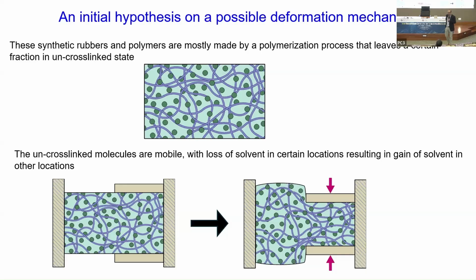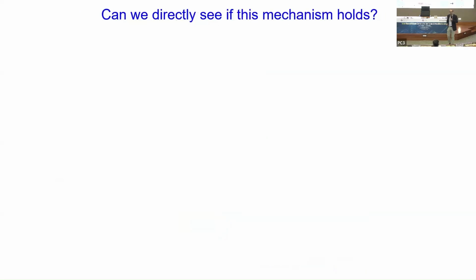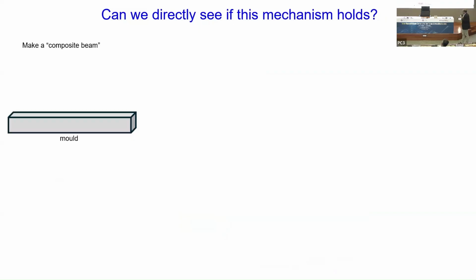Okay, so let's assume that this is the correct hypothesis, that you have a mobile species inside here. So can you actually prove that such a mobile species does exist inside this material? Can we actually directly see whether this mechanism holds? So let's make another specimen. We take a beam, and we make half of that beam from silicone rubber, but we add a little bit of zinc iodide. Zinc iodide is an interesting thing because iodine is very X-ray opaque, so it acts as an X-ray marker. So it's going to act as a tracer, but it also sticks to silicone rubber molecules. So if this zinc iodide moves, I'll be able to see it inside by my X-ray method.